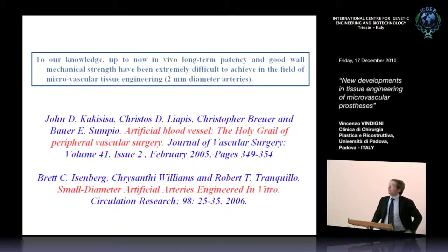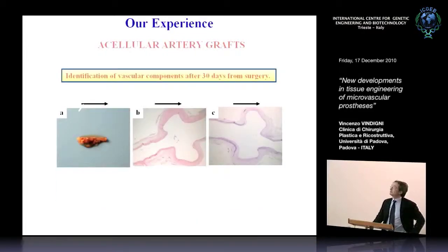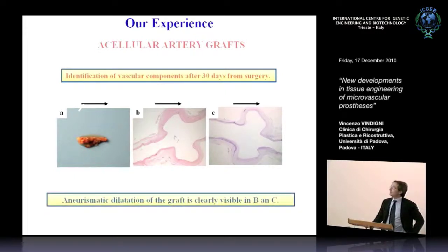Up to now, good in vivo long-term patency and good wall mechanical strength have been extremely difficult to achieve in the field of microvascular tissue engineering. We intend microvascular tissue engineering when we speak about vessels with a 2 millimeter diameter. We started our experience using an acellular artery graft, but we haven't got good results. We have a high incidence of aneurysmatic dilatation. Then we shifted our attention to bioresorbable biomaterials,